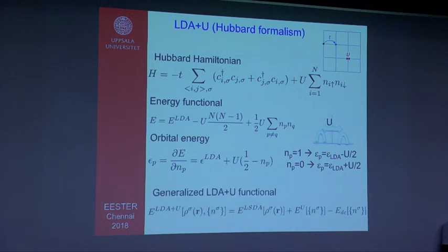And of course, a generalized LDA plus U functional is written similarly, but in a little more rigorous way. You can see that it has three parts once again: the LSD energy, the Hubbard U term, and the double counting term. Now the LSD energy, we know that when you talk about LSD, it depends on the electron density. It does not have an orbital character there. But this term and that term, these two terms, have the orbital occupation. So one can call it a kind of mixed approach. You have the density as well as the orbital occupation.